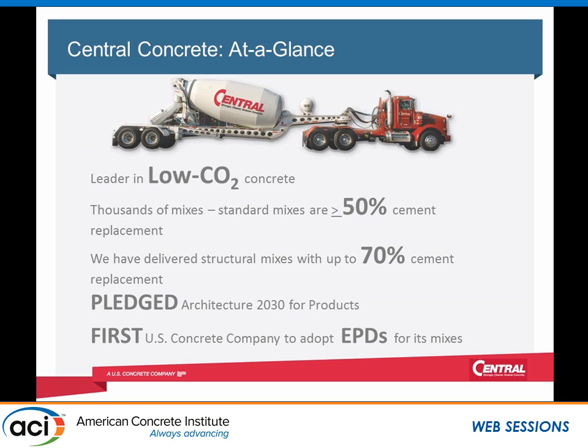We've done structural mixes up to 70% cement replacement. What that's not typical of is where you start talking about percent replacement and people take a 6-sack mix, add another 2 sacks on top of that, and replace 50% of 800 pounds. All of these mixes that we have are standard compared to straight Portland cement. So it's 500 pounds of Portland cement for a normal mix design, 500 pounds of total cementitious. We cut out half of it. We've done mixes up to 70% replacement, and I'll show you a couple of projects where we've done that.